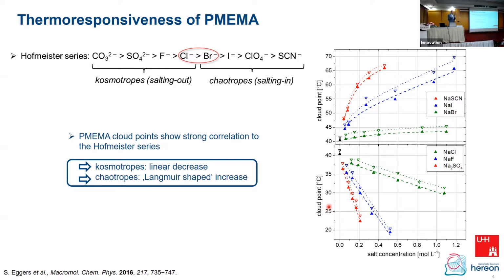Steffen then was interested in this salt influence on the solubility of the polymer. This polymer shows a lower critical solution temperature in water. And the type of salt which you add, and especially the type of anion, influences the position of this cloud point or lower critical solution temperature, which is of course a particular point in the phase diagram. More correctly we should say the cloud point, but sometimes this nomenclature is a little bit mixed up. We talk about the point where you go from a transparent solution to a phase separated turbid solution.